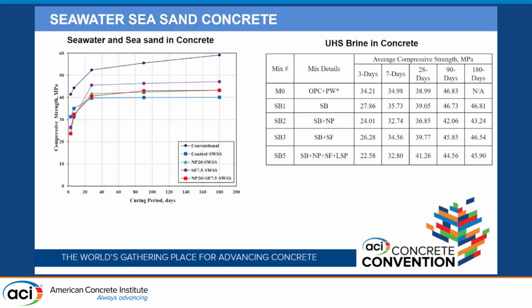I didn't present the other two parts which we have done, because some part is not completed in that particular research. In the case of seawater and sea sand concrete, there is a significant reduction in the strength. And for the ultra high salinity brine concrete, we also managed to get almost 45 plus strength in 90 days. So that also shows that with a very, very high salinity brine, you can still get a very high compressive strength. It was a very rough and tough mix, but it was good.